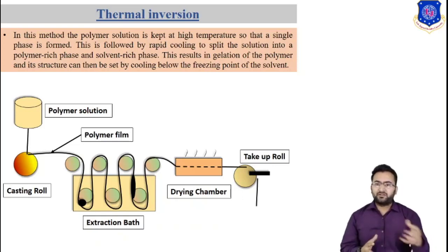Finally, a second solvent, known as a non-solvent, can be used to leach out the solvent. The usage of different solvents and combinations thereof results in membranes of different average pore size and pore size distribution. On completion of solvent exchange, the membranes are transferred where the solvent is slowly evaporated. This method is used for the manufacturing of polypropylene, polyethylene and polyolefin membranes.